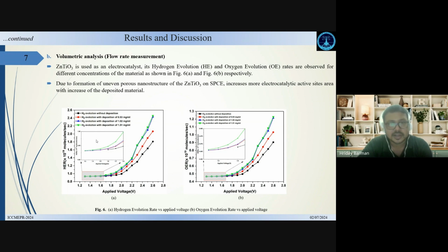But after increasing a certain amount of deposition material, that is after 1 mg per ml, if we increase to 1.5 mg per ml, then we are getting almost the same results for the 2 electrodes.